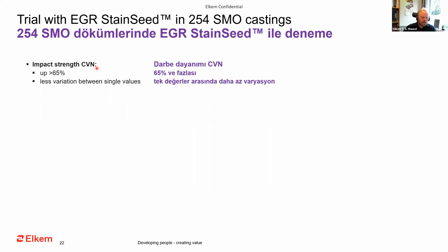But when they started to use EGR Stainseed, the Charpy impact properties went up more than 65%, and they saw less variation between the single values. As you all know, during Charpy testing, you have 3 samples that you test, but the variation between each of these samples was very, very little when they started to use EGR Stainseed.